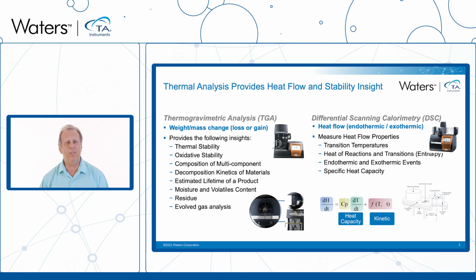And some of the things that TGA can tell you are things like thermal stability, which is stability of a material within an inert atmosphere, such as nitrogen or argon. Can also talk about oxidative stability, which is stability of a material as it's exposed to oxygen. These pieces of equipment are very good to add spectrometers such as mass spec or FTIR to them, because then you can understand the chemical nature of the gases that are evolved during the experiment. And you can also study kinetics of decomposition and potentially understand lifetime of material components.